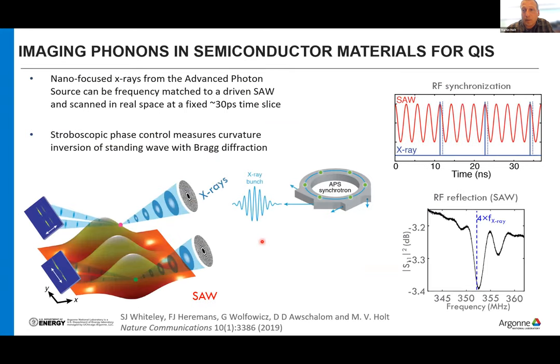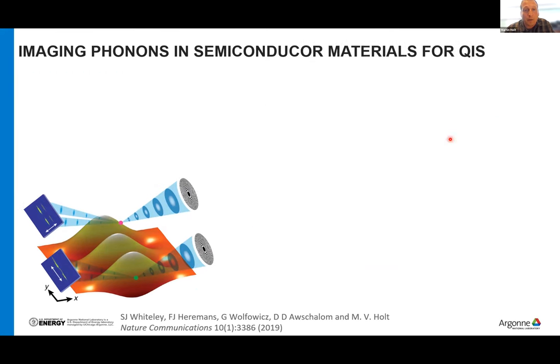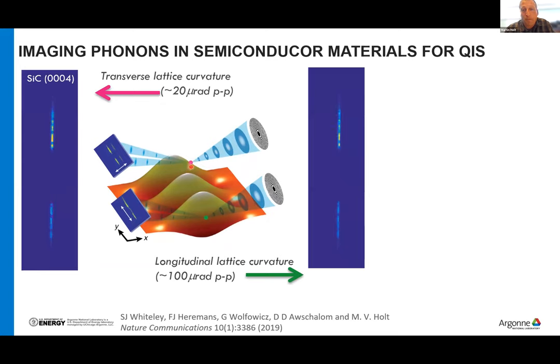And we can look at this with the synchrotron, matching up these X-ray pulses with the higher frequency acoustic wave. This can be up to gigahertz style. You're missing a lot of these waves, but then you come in at the same point in each of them. And then you can advance the phase to be able to map out the curvature. So you map in two dimensions at a fixed time slice. So if I pick a fixed spatial position, I can see this temporal oscillation directly on the detector.